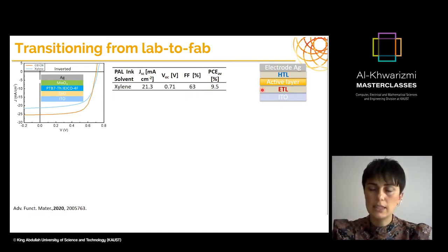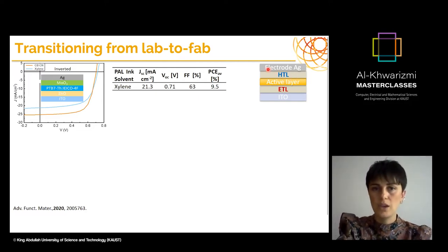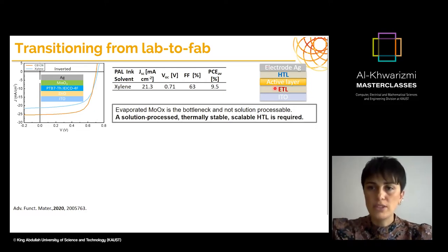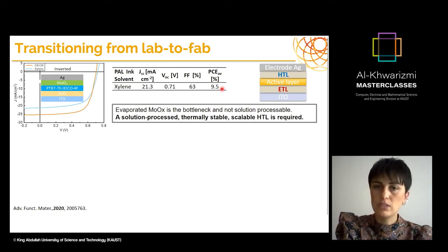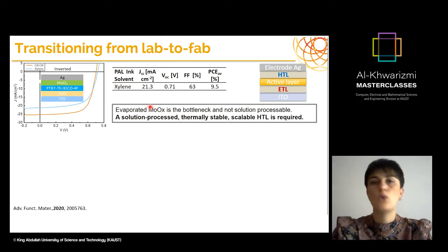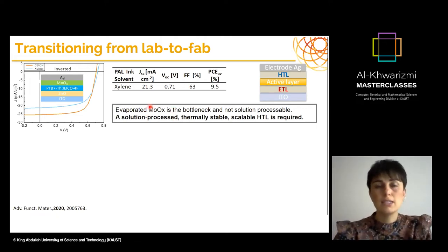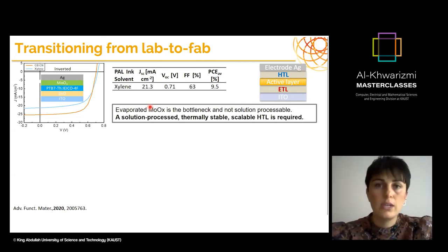And here you see the design architecture for the photovoltaic device, where you need to have an electron transport layer in this architecture, the photoactive layer, a hole transport layer, and an electrode, which is in this case silver. So we can process all these layers from solution and actually print. However, on the hole transport layer, in order to get these performances, we need to evaporate the molybdenum oxide, which is actually a quite effective hole transport layer. However, it is not thermally stable, and also it's not scalable, as I said, or compatible with printing.